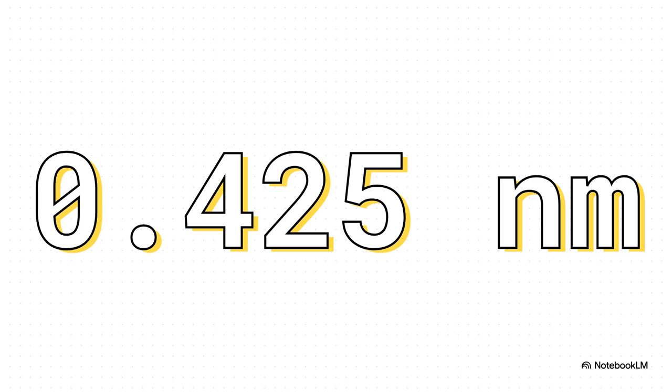That's the benchmark. It's a number that's been confirmed over decades using all sorts of different, much more complicated experiments. And the result from their two-tilt test, get this, 0.424 nanometers. That's an error of less than 1.3%. It's just incredibly accurate. It was the proof.